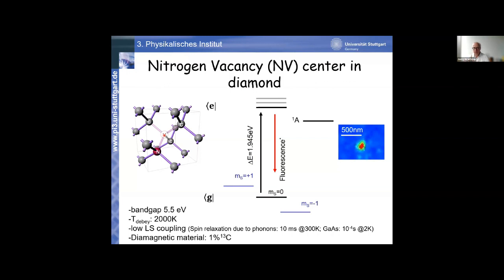This m_s=0, +1 and -1. And by means of optical selection rule, it is this m_s=0 which is the level from which you excite the system and get fluorescence. Whereas these other spin sublevels generate dark states, that is, fluorescence intensity is way reduced if the spin is in one of these sublevels. So, for example, if you take microwaves, on the order of gigahertz, 3 gigahertz typically is the frequency we are working with, you can actually pump the system, if you like, to one of these states, say m_s=-1, and then the fluorescence is reduced.